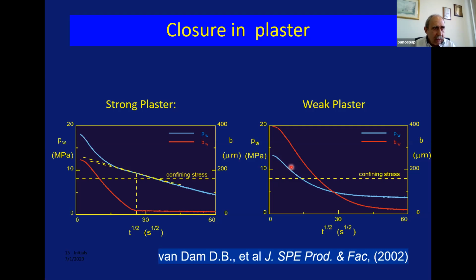Now, if we go to the weak rock or weak plaster, you can see that when the pressure drops to the value of the confining stress, which is around here, the fracture is still open, widely open. And actually, it will close the fracture here at negative net pressure, at pressures lower than the confining stress. So again, we need to be very careful with interpretation of the mini-frac in weak formations.